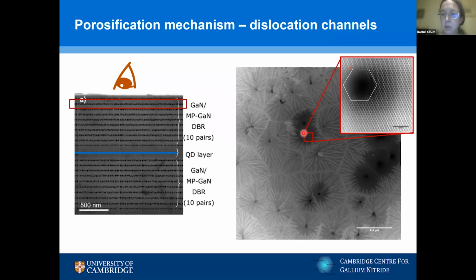If we then zoom in on one of these little black holes, this is now an atomically resolved STEM image of such a hole. What we've done is drawn what's called a Burgers circuit around that hole. Now, a Burgers circuit is a circuit that if you draw it in a perfect crystal, it closes. So we take a fixed number of steps in each of our 6 symmetry-related directions, and we should come back round to the starting point in a perfect crystal. But going around this hole, we don't close that circuit. There's an error in closing the circuit of essentially 1 lattice spacing. That's what we call the Burgers vector. And that shows that what there was at the center of this hole is a dislocation core.